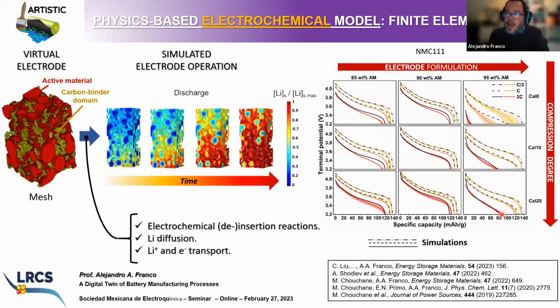In order to do so, we apply a technique called finite element method. This is a model that we co-developed with Jorge Vázquez Arenas, as I mentioned before, in 2017, and then we improved it a lot with new functionalities and so on and so forth. In particular, we improved it by considering explicitly the spatial location of the carbon binder domain in the electrode volume. And then by performing meshing of the electrode microstructures arising from the manufacturing simulation, and by implementing the physics going on when this electrode is operating in a lithium-ion battery cell, which is being discharged and charged and so on, we are able to predict the lithiation and delithiation dynamics in the 3D volumes.